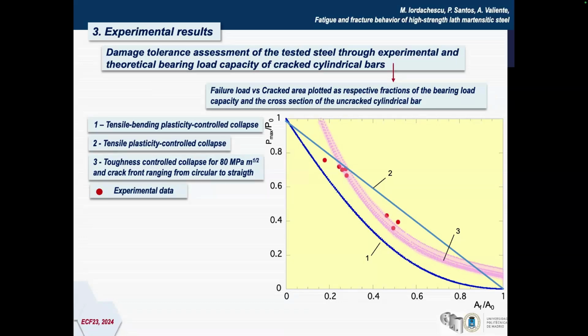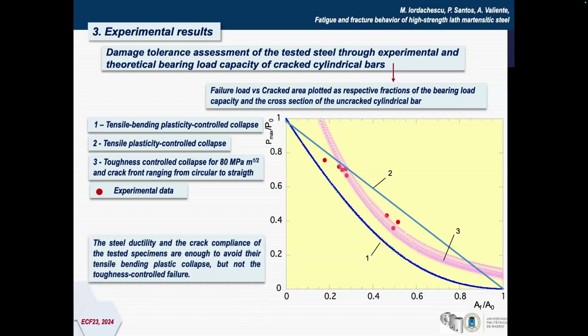Here we have, with red dots, our experimental results from the fracture tests, and then we have some theoretical lines that indicate the first, tensile bending plasticity controlled collapse. The second line is pure tensile collapse, and the third, which is in pink, is toughness controlled collapse for 80 megapascal square root of meter, and crack front ranging from circular to straight. So what we can say is that the steel ductility and the crack compliance of the tested specimens are enough to avoid their tensile bending collapse, but not the toughness controlled collapse.